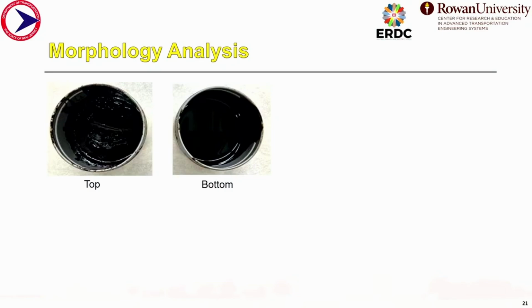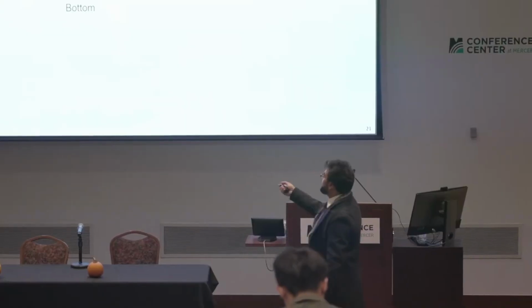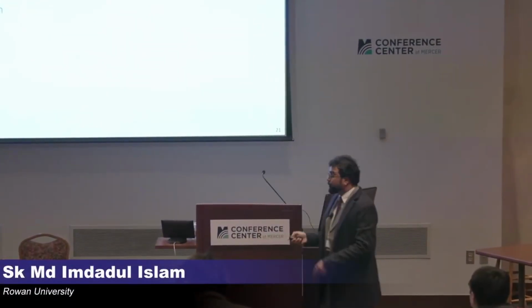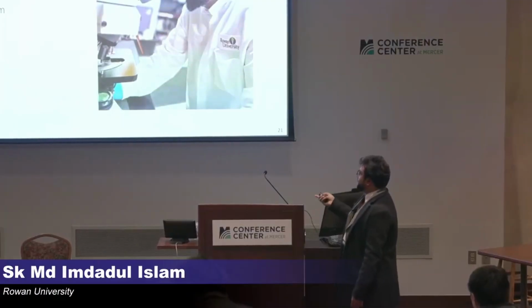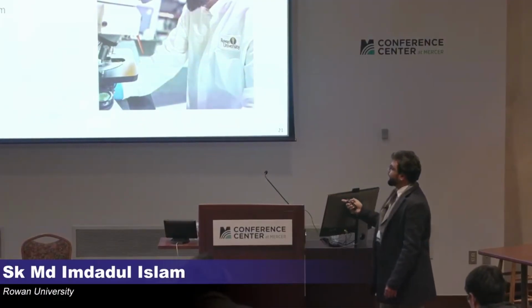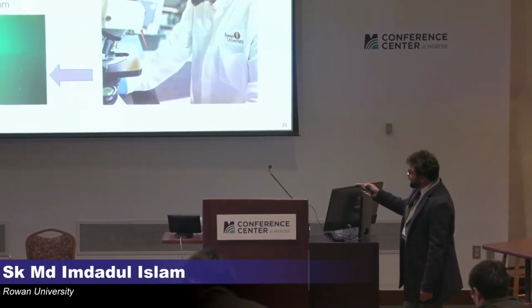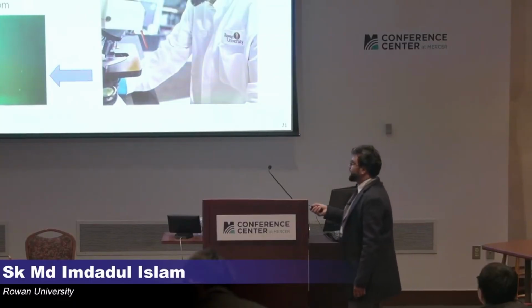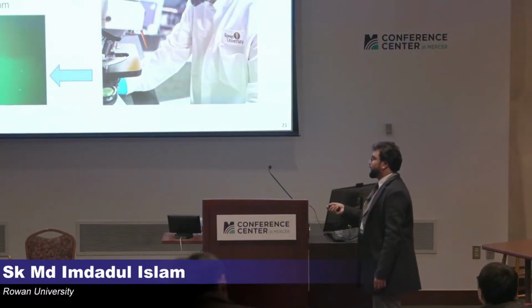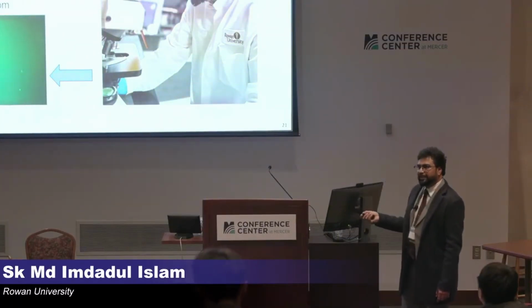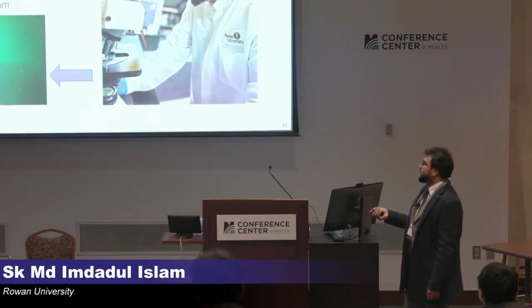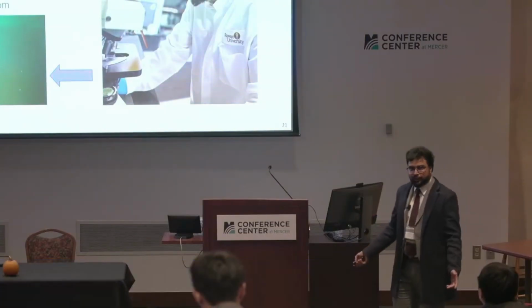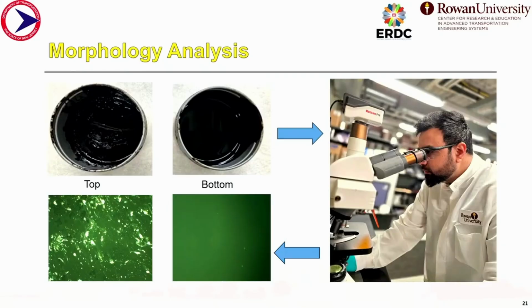So we can see the top portion of the binder and the bottom portion from the tube that we get after the polymer modification. We did the fluorescence microscopy using a fluorescent microscope, and we can see the difference clearly at the top. The white globules are the presence of plastic at the top, and at the bottom we can see there is no plastic. This is called the phase separation, and we can clearly see it from here.